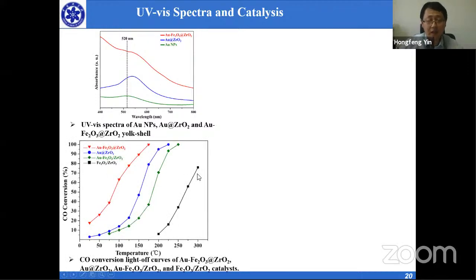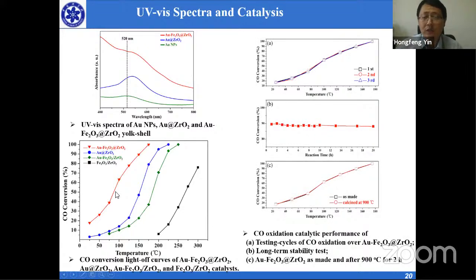For the catalysis, when there's only iron oxide, it has very bad catalytic ability. When there's only gold and iron oxide or zirconia, without this kind of core-shell structure, the catalytic ability is as shown. With introducing our target core-shell structure, you can see that the catalytic ability increased a lot. We also did this reaction a couple of times, and you can see that there's almost no change. That means this structure is pretty stable. And we ran a long-time reaction, and there's almost no change.